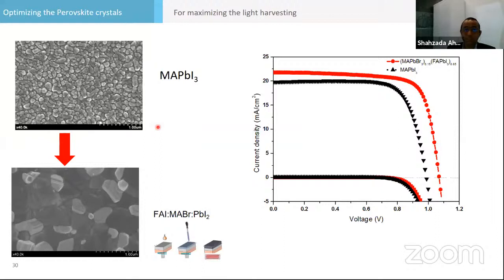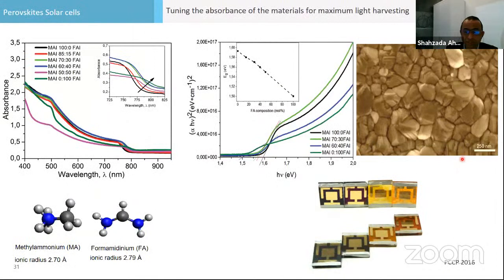So in 2012, when we started working, we were working on methylammonium lead triiodide. You can see the crystal size is so small, and there were more crystals. The higher the number of grain boundaries, the higher the charge recombination, the breeding ground. After working for so many years, and everybody coming with a new composition, you can see the crystal size is now bigger. This is mine, very old work, but now the crystal sizes are much bigger. Others have shown it too. The grain boundaries are fewer, so recombination is less. We do solvent engineering, putting a solvent drop in between to increase the crystal size, and you can see in a representative graph how the efficiency has increased.